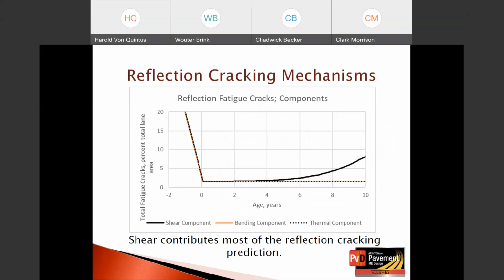This first graph shows the reflection fatigue cracks in each of the individual components shown at the bottom: shear, bending, and thermal, and their importance or their proportion of the total fatigue reflected cracks in terms of percent total lane area over a 10-year design life. As you can see, the shear component, which is the black solid line, represents the majority of the damage resulting in a reflection crack.